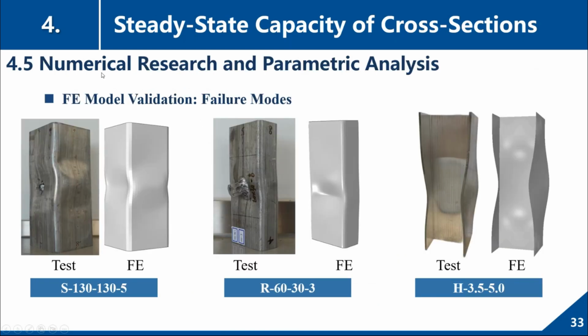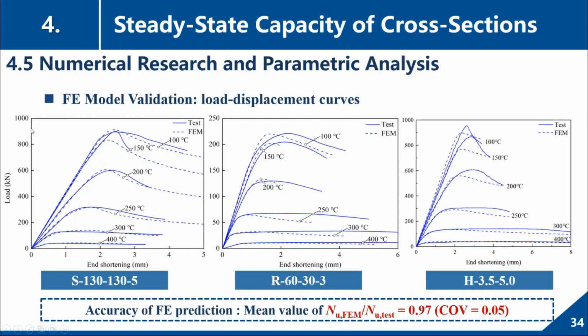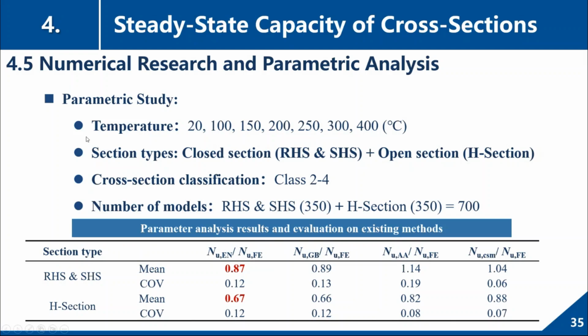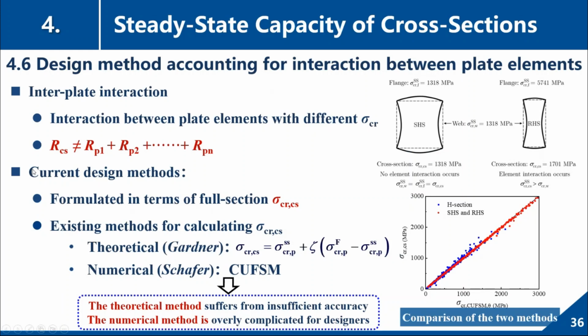And after tests, we developed an FE model and validated the models. And these are the validation of the load displacement curves. And we got a very high accuracy of the FE prediction. And then we used the FE model to carry out a parametric study. The number of the models is around 700. So till now, we have got all of the test data and FE data.